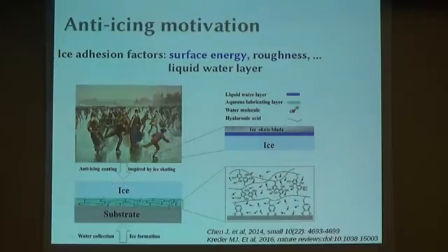And nowadays, we have some very preliminary knowledge about what is responsible for the ice adhesion strength, so to say. So I put some keywords here, one of which is the surface energy. This term means a combination of chemistry, like electrostatic charge on the surface that can attract or form hydrogen bonding to the water molecule, the so-called ice molecule.